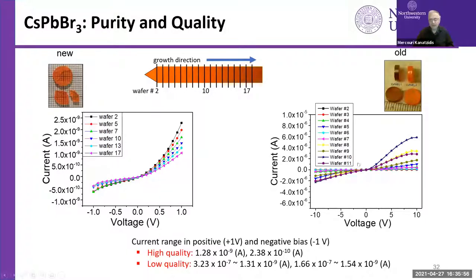So in fact, on the right, we have another ingot where we have, you see here, 10 to the minus 6 amps current. So this is a bad quality material. On the left, 10 to the minus 9, 3 orders of magnitude lower. And so this is a high quality material. It corresponds to the original material, which doesn't look very good, from 2013. This is the more recent.